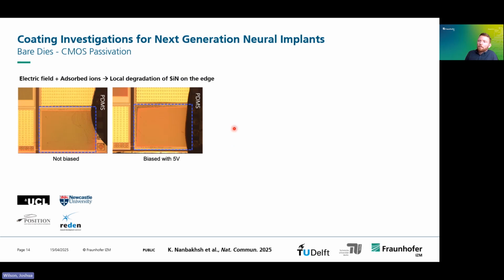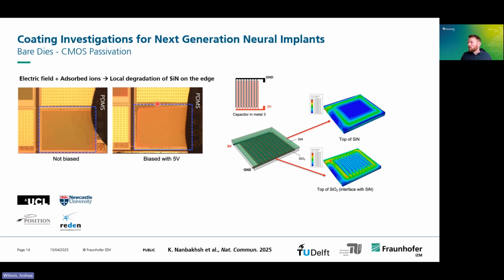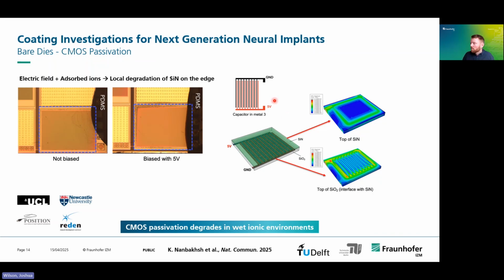But if we look more deeply, if we don't just look at the electrical characterization and we look at the surface of our devices, what we see is for the devices which were biased with this 5-volt DC, we see some degradation around the edges here. And this matches where the electric field is highest in the top layer of our chip passivation. And so what we know is happening is that the 5-volt DC bias combined with this saltwater environment is driving a degradation of this chip passivation. So in these wet environments, the CMOS passivation, while it endured electrically for a year, is already starting to degrade.